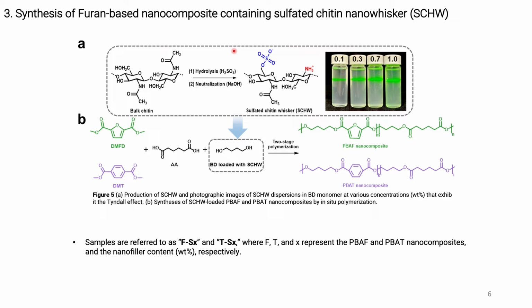The sulfated chitin was then incorporated into the polymer matrix via in situ polymerization. SCHW with high dispersibility was directly added in butanediol monomer, as can be shown in the Tyndall effect images here. The in situ polymerization involves two separate stages, which are trans-esterification and polycondensation.